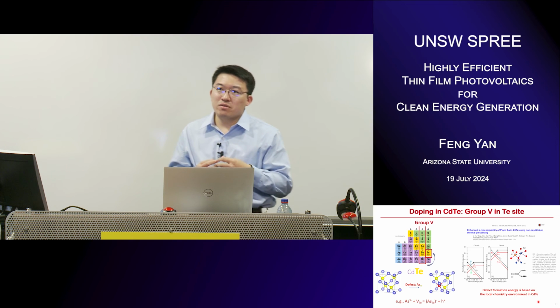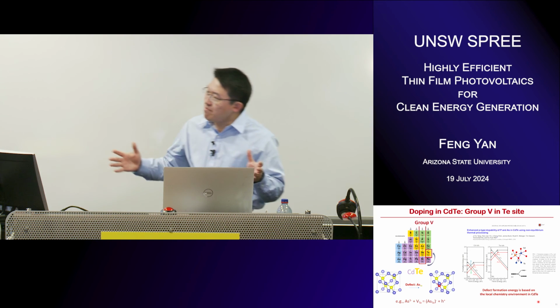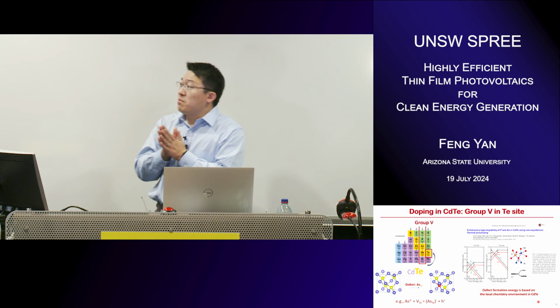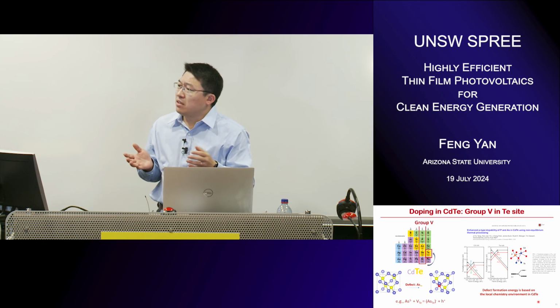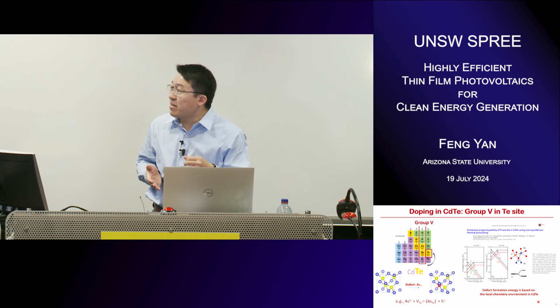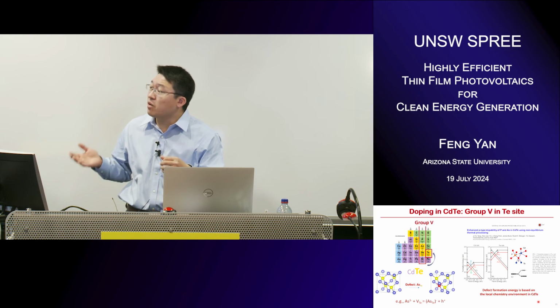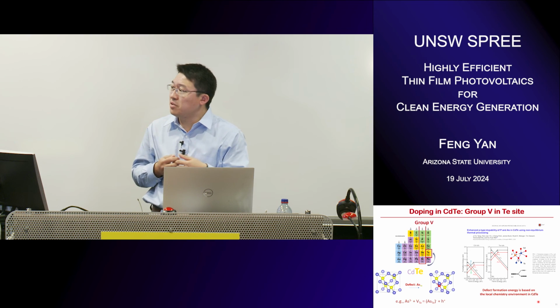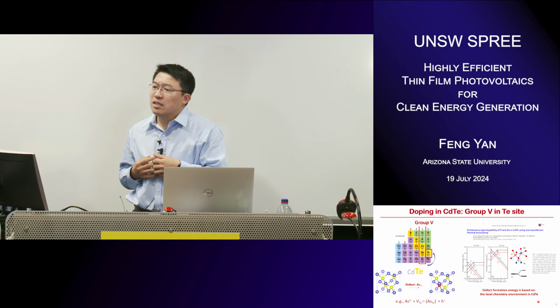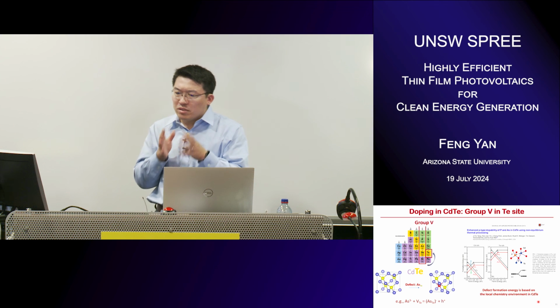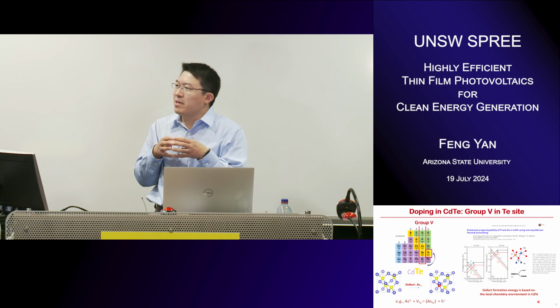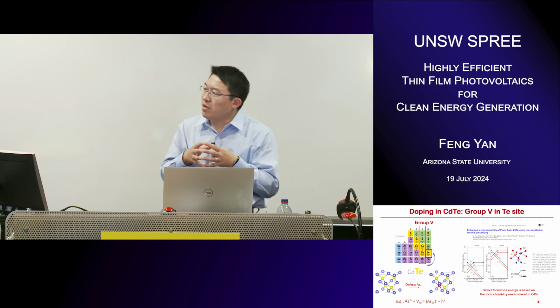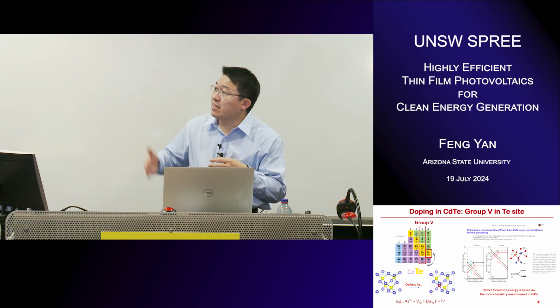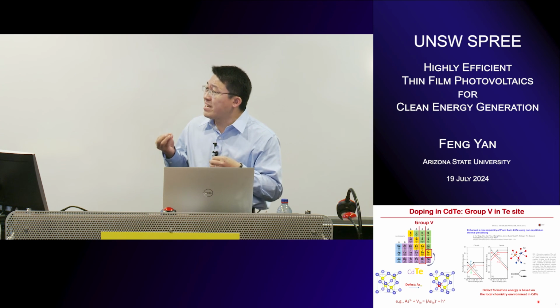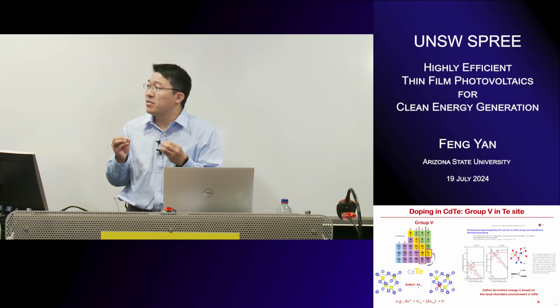We mentioned that grain size can be controlled from 1 to 10 micrometers, but the grain boundary is probably just several nanometers. From the EL or PL, we can clearly see that chlorine segregates at the grain boundary, which corresponds to the improved CL or EL signal. But for how the grain interior improved, the resolution is probably not as good as for the grain boundary, because the dominant signal, you can see, is bright if you check the EL, right?